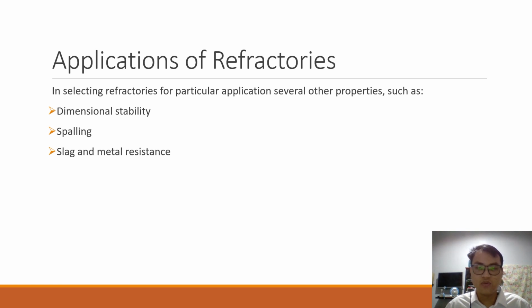Spalling refers to cracking, splitting, or flaking of the materials when subjected to sudden temperature changes, also called thermal shock. A refractory may spall in a variety of ways owing to one or a combination of causes, including temperature gradients in the brick due to uneven heating or cooling, which set up stresses of such magnitude as to cause failure. Compression due to volume expansion of a whole structure of refractories from a rise of temperature sufficient to cause shear failures. Difference in coefficient of thermal expansion between surface layer and the body of the brick, brought by surface conditions, great enough to cause breaking off of pieces. Slag and metal resistance. It is essential that refractories should not react at high temperatures with the substances they will be in contact with.